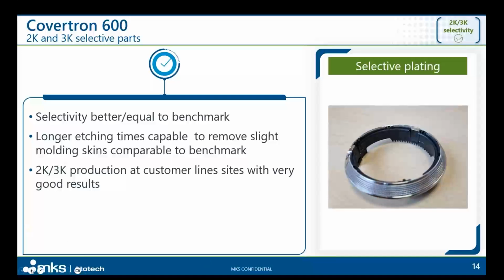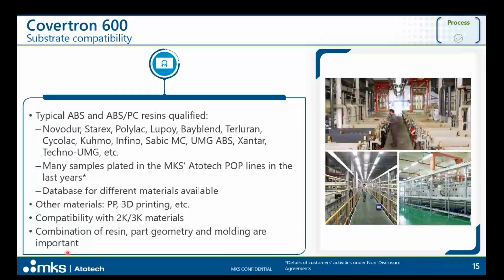One important question from your side will be, okay, what happens with the materials? The substrate compatibility is good with the Covertron 600. And yes, we can share with you that the list of plastic substrates which have been processed through our Covertron 600 is long, and shows that the substrate compatibility with this etching process is excellent, without being necessary to modify the resin, or change the existing resin by specific modifications to be able to process the parts through a chrome-free etching process.